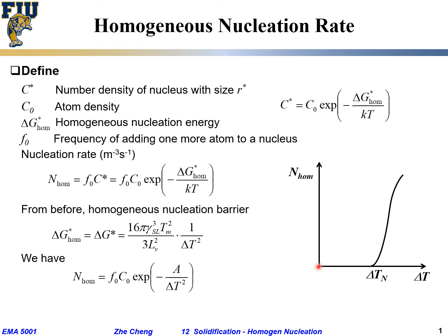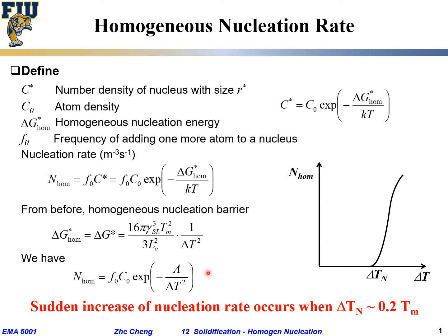When ΔT is relatively small, the homogeneous nucleation rate is essentially zero, until it suddenly starts to increase exponentially and then reaches a kind of saturation. What experiments show is that this sudden increase in homogeneous nucleation rate occurs when the nucleation undercooling ΔT_n is around 0.2 times the melting temperature — meaning about 20% below Tm — at which point homogeneous nucleation for solidification suddenly starts to occur.